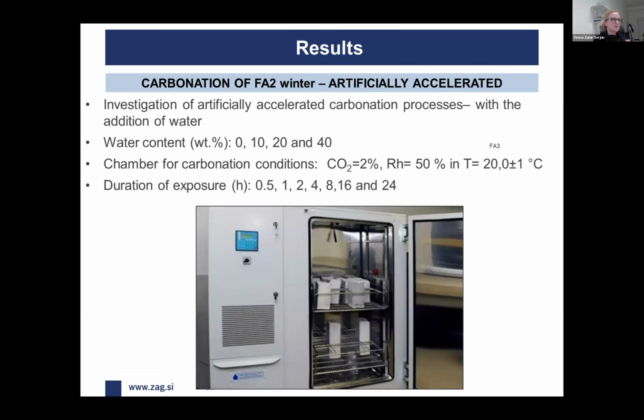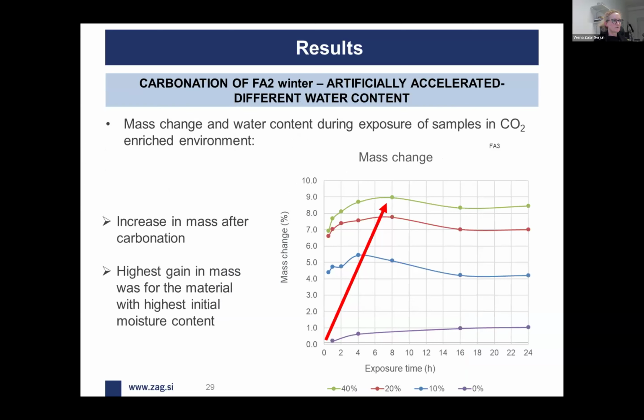So when we proved that the water content is a very important parameter in increasing the carbonation process, we took a further step to investigate the carbonation mechanism by adding different quantities of water to the ash and using chamber conditions with 50% relative humidity and a high CO₂ concentration. In the first step, we took short time intervals, from half an hour to 24 hours.